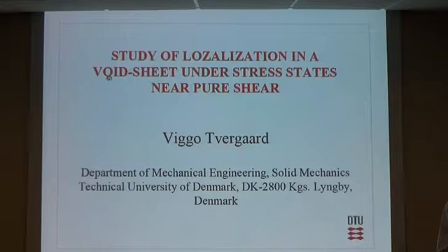The kind of results that come out of this, if this ratio is equal to 0, this is pure shear. You see that the voids become microcracks, they grow completely into microcracks, and there's no tendency of failure at all found here. Various things were investigated, but it was not possible to find a mechanism like that in simple shear, where the voids would explain failure in this study.